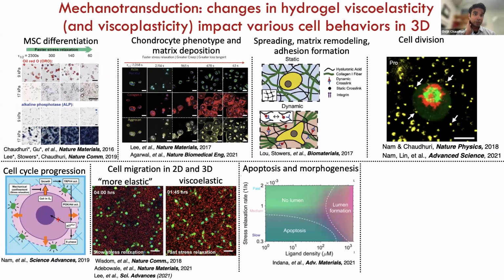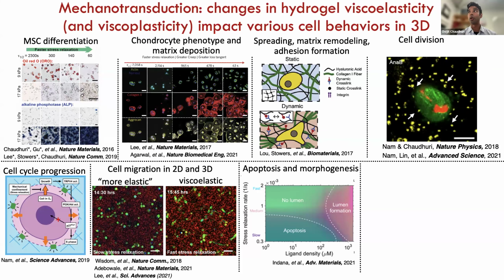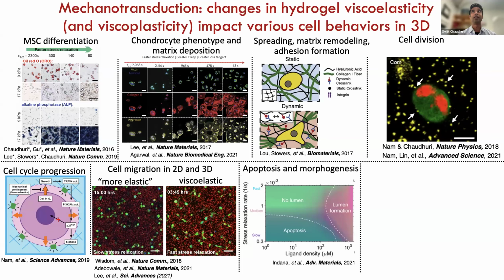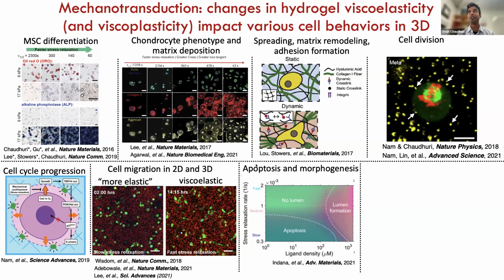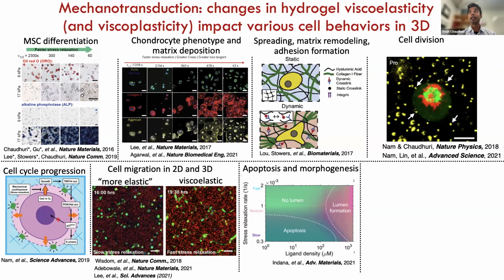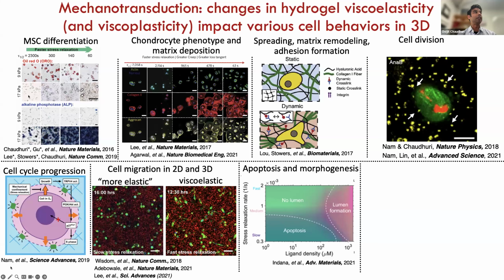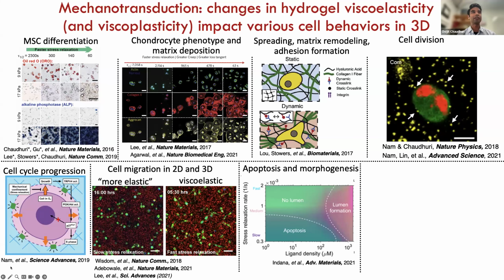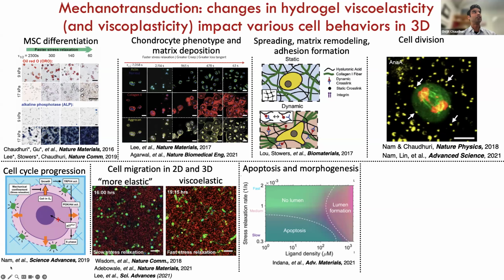Okay, so as I mentioned, we spent a lot of time, and we've published a few papers looking at the impact of viscoelasticity on cells, and I'm showing some snapshots from these different studies here. We started out by looking at differentiation of mesenchymal stem cells, and we see that if you have a stiffness of 17 kilopascals, and you go from slow relaxing to fast relaxing hydrogels, the osteogenic differentiation, as indicated by staining for alkaline phosphatase, is enhanced. We also saw that the osteogenically differentiated cells were able to form a more bone-like matrix consisting of type 1 collagen and mineralized matrix, something that looks a lot more like bone.